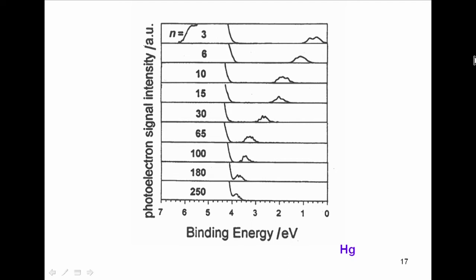Well, let me tell you in words, I've limited the number of frames because of the time I have. Let us take gold. If you have a block of gold, or gold in my ring, it has the same properties. However, if you make a small particle of gold, say 1 nanometer or 2 nanometers, it is no longer the same. It becomes very reactive. It is no longer metallic. Gold ceases to be metallic when it has about 200 atoms or so, around 1.5 to 2 nanometers and below. And this is one experiment done many years ago in Israel and also in my laboratory.